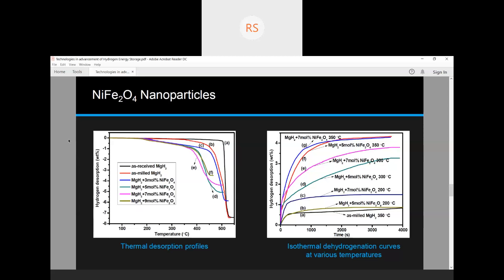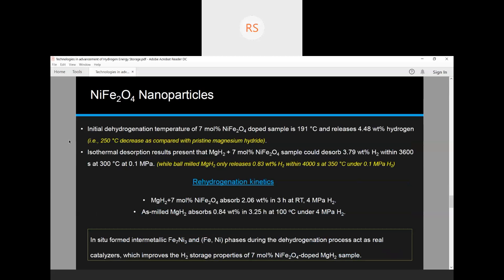The profile possesses a more excellent catalytic effect on boosting MgH2 dehydrogenation kinetics properties. Also talking about the rehydrogenation kinetics of this system, the doped sample absorbed 2.06 weight% in 3 hours at room temperature, while the pristine sample absorbs 0.85 weight% in almost 3.5 hours at 100 degrees centigrade. So here we can notice the desorption conditions are improved, the time is improved, and the temperature conditions are also improved.